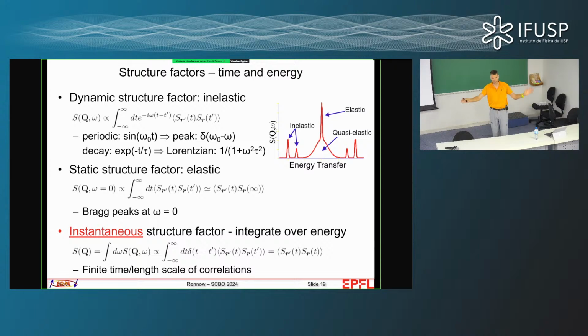So which are vibrations of the crystal lattice. If I have a magnetic system, I can have a similar magnetic oscillation that will have a characteristic frequency, like sin(ω₀t). Once I Fourier transform that with respect to time, I get a delta function in frequency. ħ times frequency is an energy. So when I do an energy scan of neutron scattering, I would see peaks corresponding to the frequency of the fluctuations in my sample.